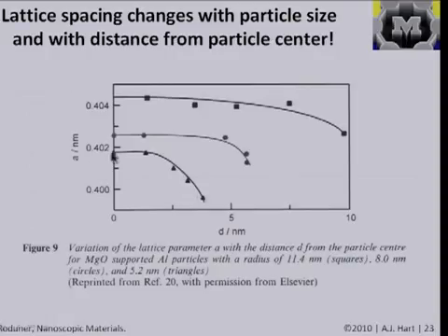It shows that at the edges of the particle, the lattice spacing is smaller than in the center because you have more of a local effect of this surface pressure. So there are manifestations of this surface stress in changing the positions of the atoms and what they're locally feeling. There are certainly differences between what the surface atoms feel and what the bulk atoms feel as well.